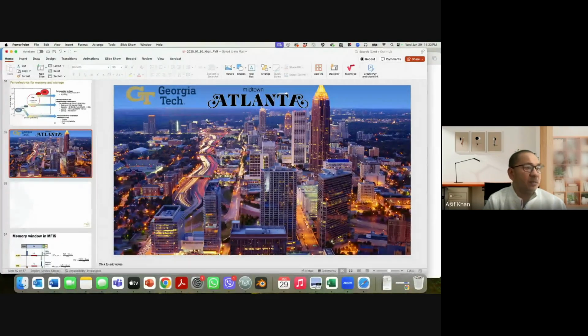Now, the second question about reliability is very important. Initially, we thought that these devices wouldn't be reliable because they're basically depending on the traps. But to our surprise, as I was showing in our recent work on retention, the devices actually have very good retention. So check mark on that one, these traps do not impact the retention. And endurance-wise, what we see is that these devices, with or without this alumina layer, have the same endurance. So basically, alumina does not impact endurance.